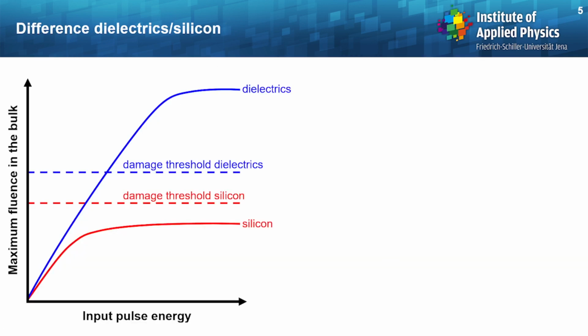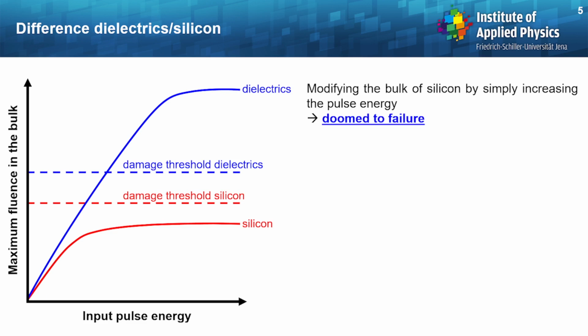Okay, so now this is probably the most important figure of my talk, actually. If one tries to compare dielectrics and silicon, one can represent the maximum fluence that can be reached in the bulk of the material as a function of the input pulse energy. For dielectrics, in blue, you can see that it is possible to cross the modification threshold. For silicon, in red, because of filamentation, we have this saturation, and it appears that this saturation is below the damage threshold of the material. In other words, if one tries to simply modify the bulk of silicon by a simple increase in the input pulse energy, then this strategy is doomed to failure.